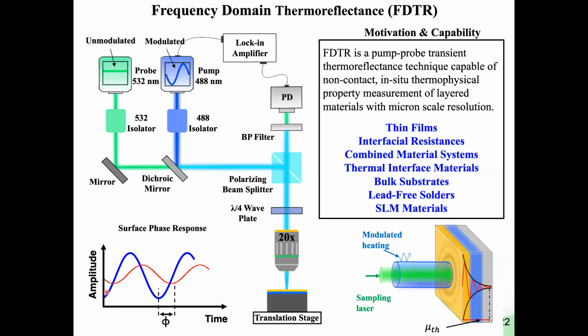And if we look at what's happening, this is the laser flux in blue. We'll see that the temperature response of that same point is also sinusoidal at the same frequency, but it's slightly phase shifted. So there's some lag. The max temperature comes a little bit after the max heating. And this is analogous to how max heating on Earth is around noon, and then the max temperature might be around 2 or 3 p.m. So this phase lag between the max heating and the max temperature will actually indicate the thermal properties underneath the material. And depending on how fast we modulate this laser, so the laser is turning on and off periodically, the thermal wave can penetrate just a short distance into the material. So we can measure very local properties.